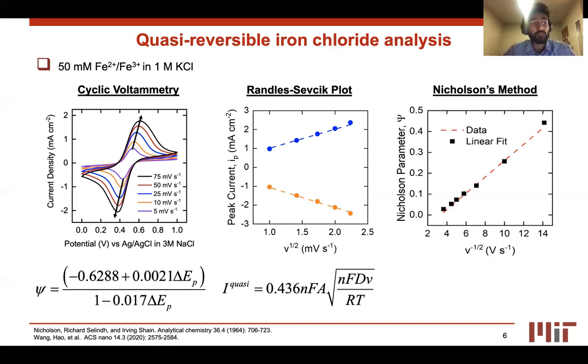Lastly, Nicholson's method was used where Nicholson's dimensionless parameter psi was calculated using the peak-to-peak separation obtained from the CV, and the plot against the inverse of the scan rate square root was generated. The kinetic rate constant was then calculated using the slope from the linear fit in the Nicholson's plot, combined with the diffusion coefficients obtained from the Randles-Sevcik analysis.